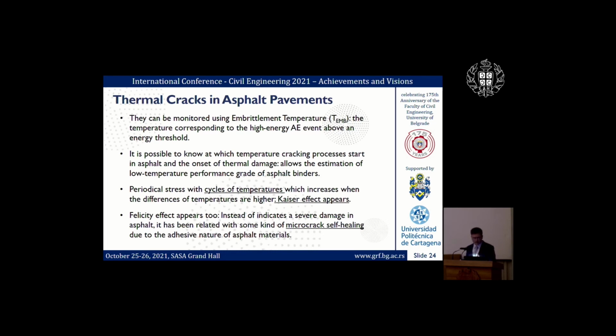but with a special characteristic: it is now not related with damage, but with some kind of micro self-healing of the asphalt, probably due to the adhesive nature of the materials. So when we have acoustic emission, but prior with a difference of temperatures that is lower than the previous one, it can be an indication of this self-healing.